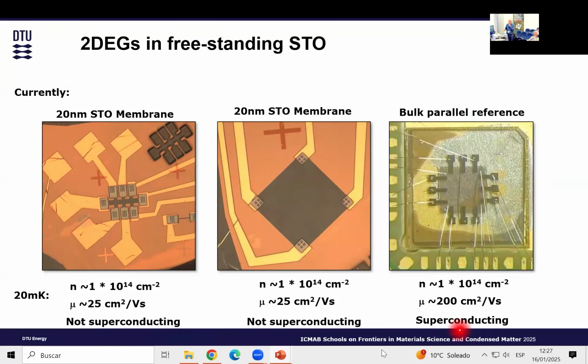And then we tried to look for superconductivity. We can only get superconductivity here. We could not get it here. So it has something to do with the mobility of the material, which we need to solve. We think, and we are still trying to understand, that it has something to do with a polymer layer, a very tiny residual of polymer layer or any other contaminant that we have on the surface when we transfer the first layer to put it. So we need to clean it. We need to make sure that it's clean, because if it's not clean, we think that this is what reduces the mobility.